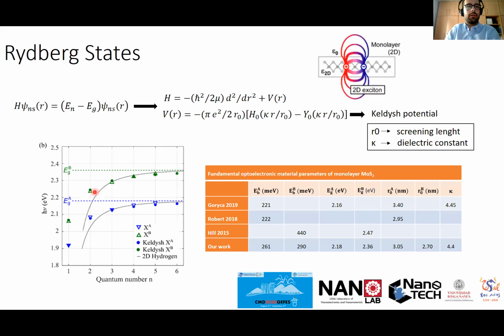Here we have the experimental data and the theoretical data. And we observe that the 2D hydrogen model that is solved using a Coulomb potential does not fit very well. We have here the fundamental optoelectronic parameters of the material. And here we observe that with these two works, we have very good results that are very similar. But this other work is different, it has different parameters. We attribute that to the mislabeling of the different states.